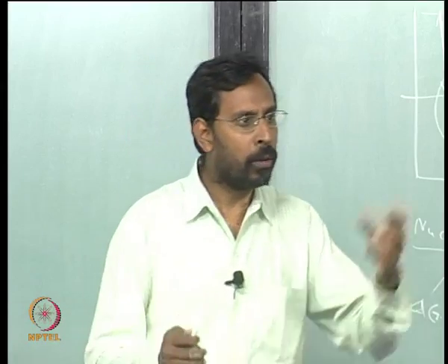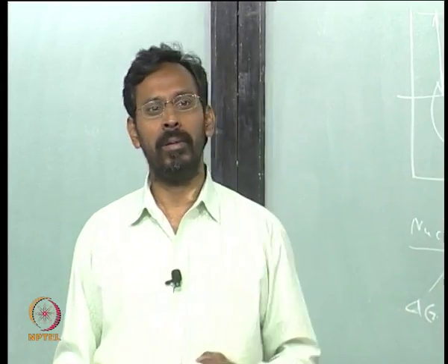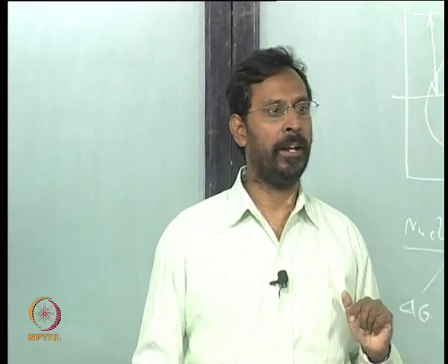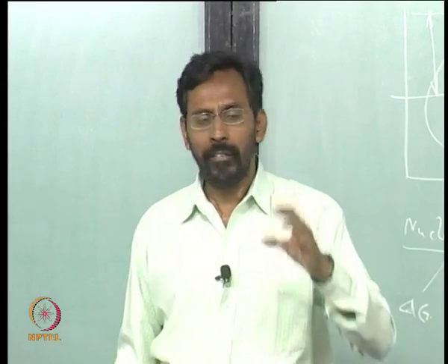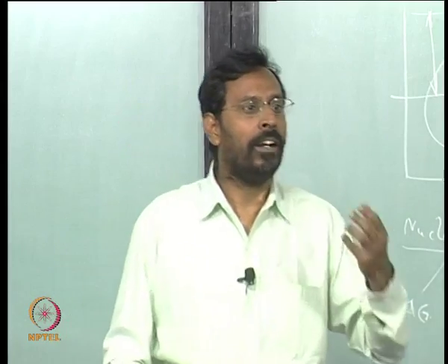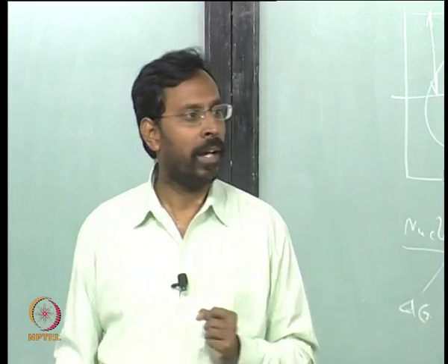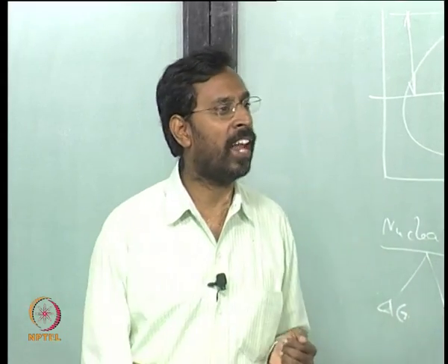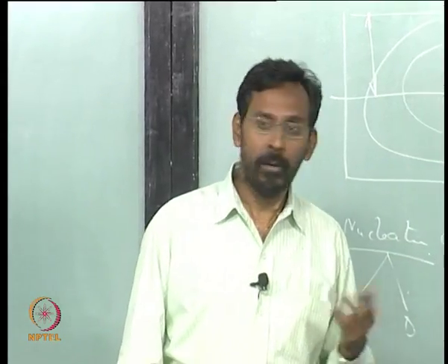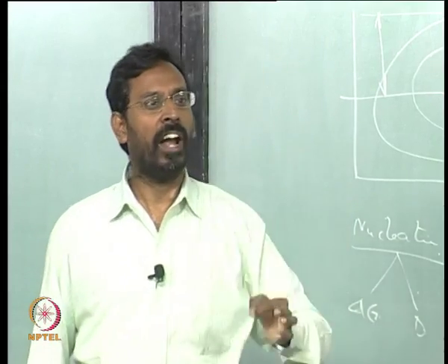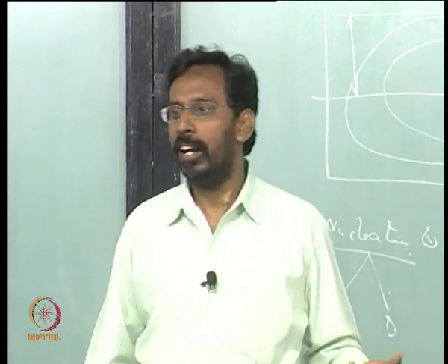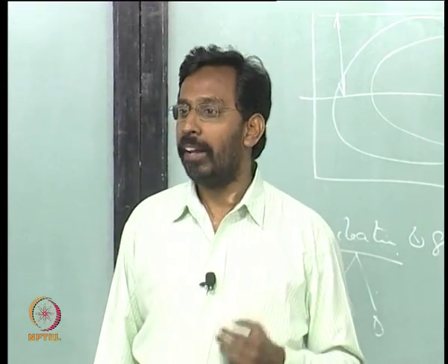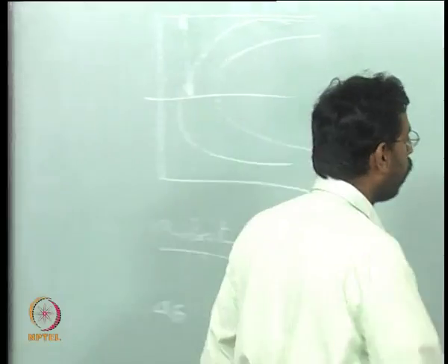Atoms coming together forming an FCC cluster or a BCC cluster is easy, but if your cooling rate is so high that even that cluster is not able to form a nucleus, then even pure metals form glasses. Pure silicon people have quenched at a very high rate and seen it become a glass. Pure nickel people have shown at rates as high as 10 to the power 12.